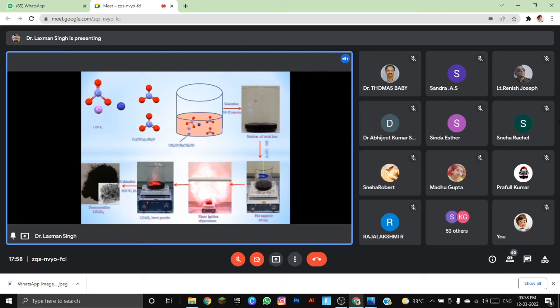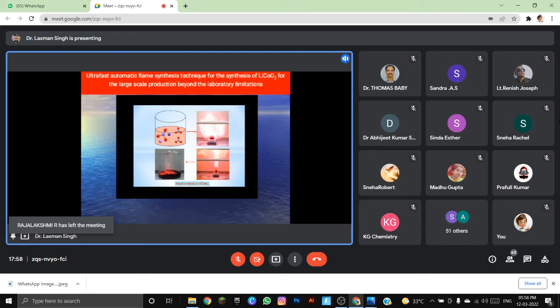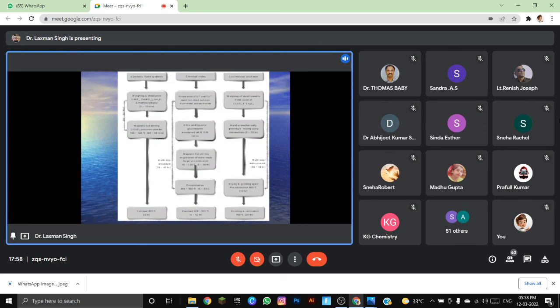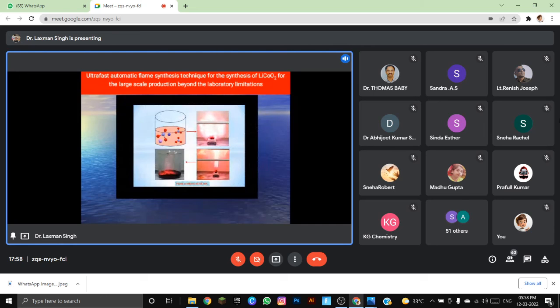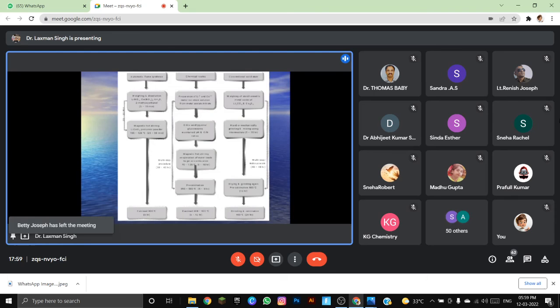A very large volume of flame is there, and then the powder is there. It is very nanocrystalline in nature, without any calcination temperature, without any sintering. We have the nanocrystalline lithium cobalt oxide. This is also known as the ultrafast automatic flame synthesis technique developed by our lab, and this will also be commercialized because we have got a patent on this, and the technology will be transferred soon.